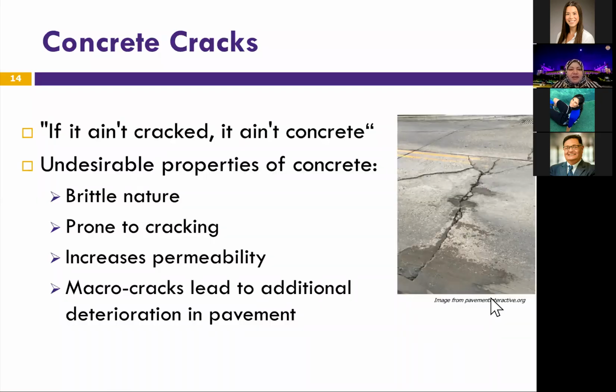There is a saying, if it isn't cracked, it ain't concrete. So we drive around all over and there are cracks everywhere in the concrete. Concrete is a very important material that we utilize not just in our pavement or even the infrastructure, but even in our commercial buildings, etc. Unfortunately, it's a brittle material, so it's prone to cracking. It also has permeability that increases over time, which allows deleterious substances to enter into the structure of the pavement, causing damage and lack of durability.